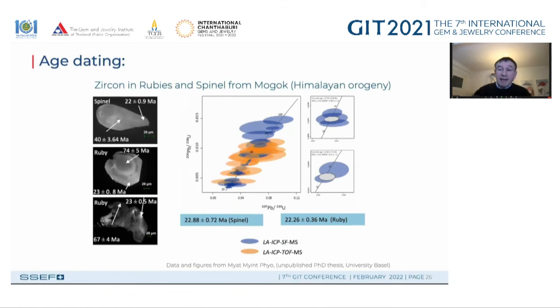Now, when we analyze zircon precisely, we will see that even if the grain is very small, very often it's not homogeneous. So we have a core which might be older than the rim which formed at the same moment of metamorphic event when the sapphire or ruby has formed. So we can have different ages depending on where we measure actually in this zircon grain. Now, when we look, however, on gemstone deposits, and as I said, Himalayan origin or Pan-African, this is such a huge time difference, so this doesn't matter so much.